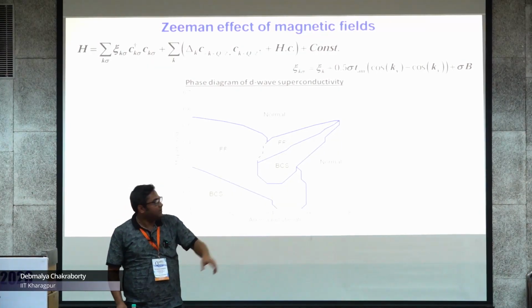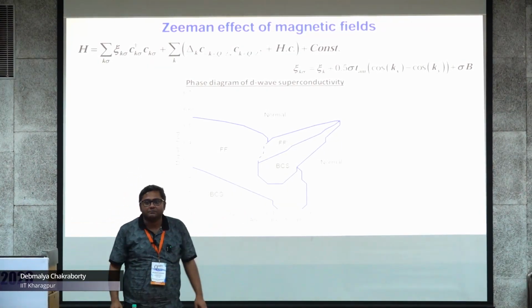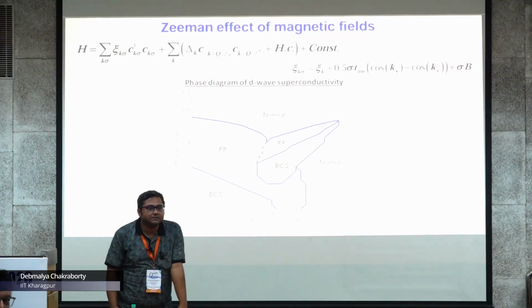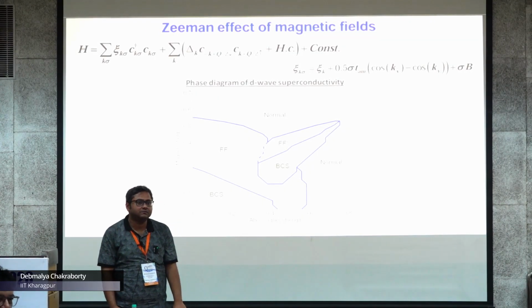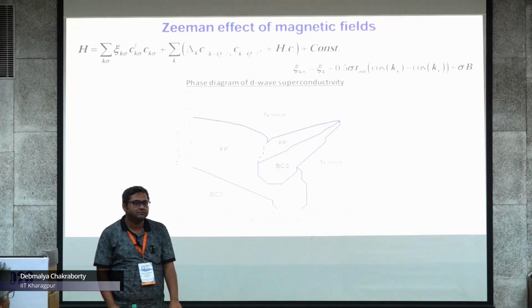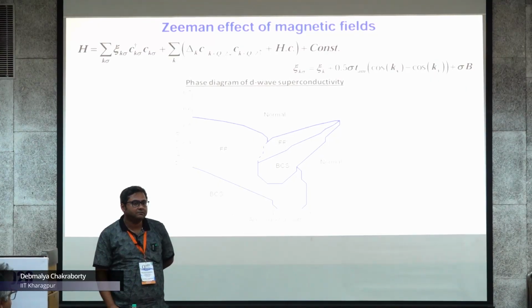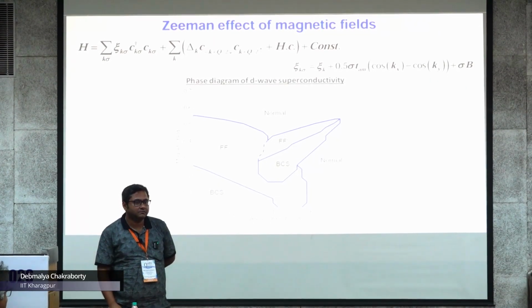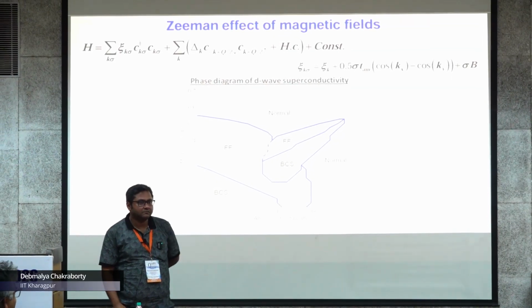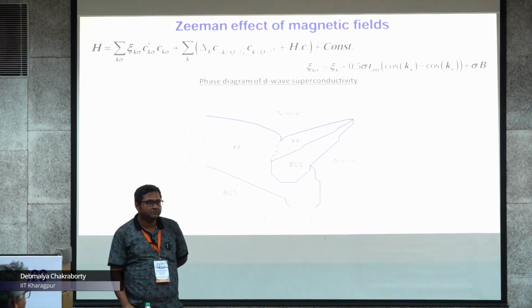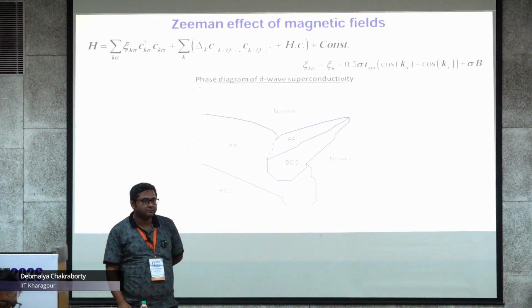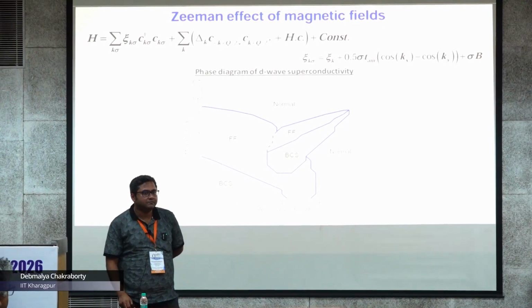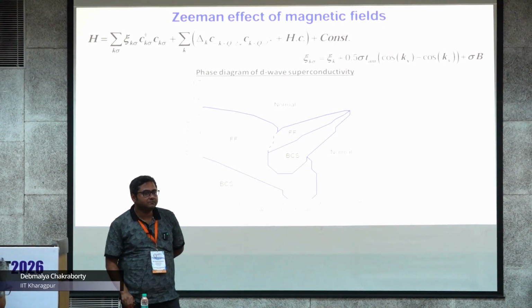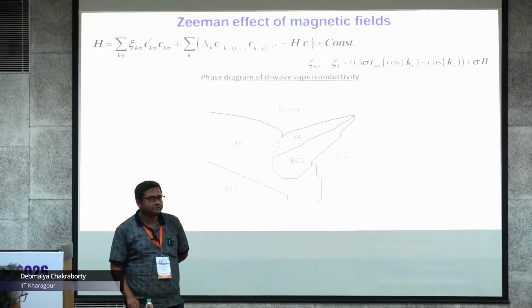In plane, just a sigma z term. One small question: of course, this is in momentum space, and some experiments on FFLO have seen order parameters which cut along the field direction. It becomes 0 as you apply the field. There are nodes in the cos Q term. So what determines that zeroing out?